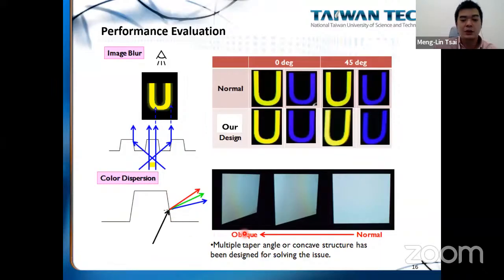So that the image blur problem can be reduced. Because your image blur is due to the total internal reflection of the sidewall, you try to come up with a rounded sidewall, and this image blur can be largely suppressed. And for the color dispersion problem, if you come up with a continuously rounded sidewall, for different angles there will be different dispersion, so you will come up with an average of a white screen. So this rainbow phenomenon, what we call rainbow Mura, can be largely suppressed.